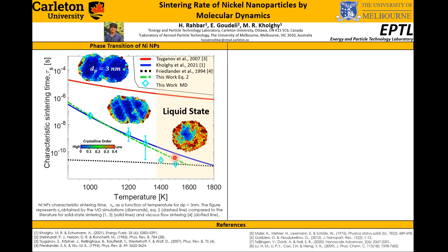Finally, we can see the values for temperatures more than 1400 Kelvin reach the asymptotic value corresponding to the viscous flow sintering. So we can see a very good agreement between the MD simulation as well as the phenomenological model.